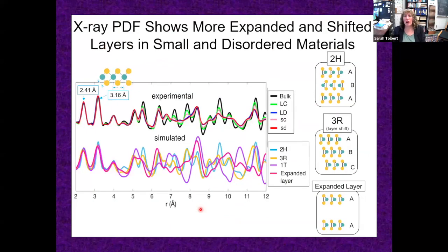Okay, there's a lot of wiggly curves here. You don't have to pay attention to many of them. We characterize the disorder using X-ray pair distribution function analysis, which is a total scattering technique that lets us look at the ordered and disordered components of a material. And what we find is that compared to bulk material, all of our nanomaterials are a little bit disordered, but the ones that we made at high temperature, that is the green ones and the pink ones, have mostly just one kind of disorder, which is where the layers slide. So they get a little bit off registry.